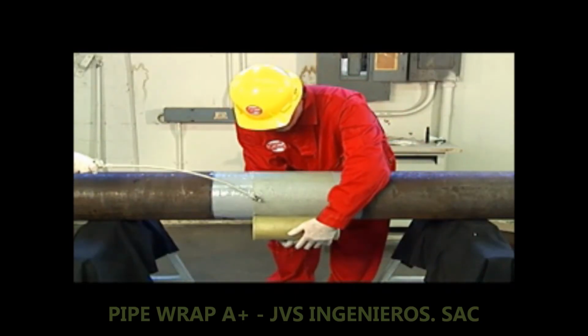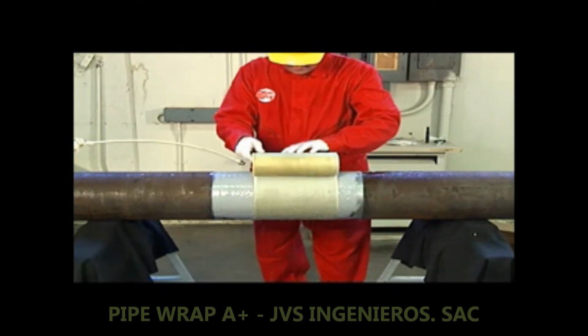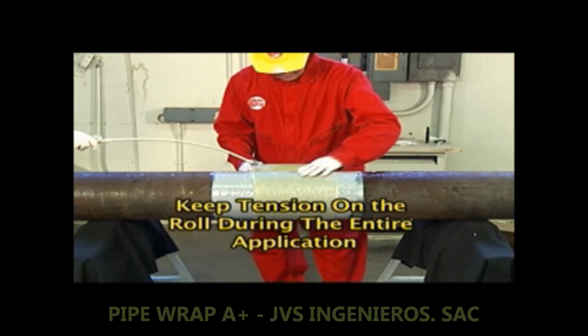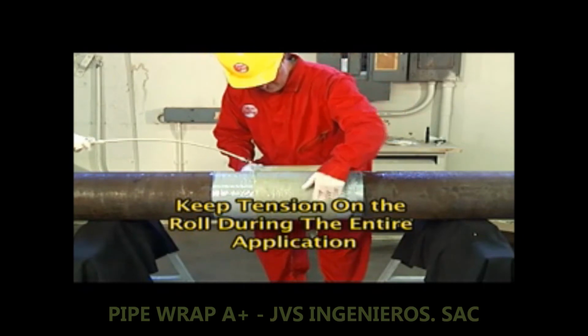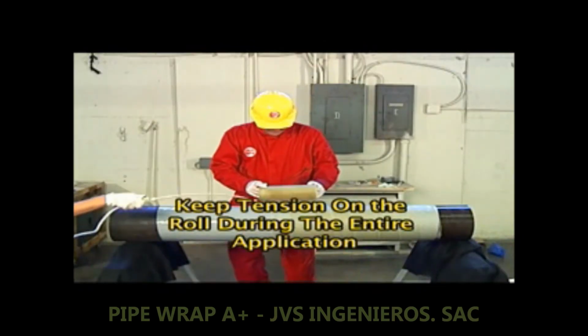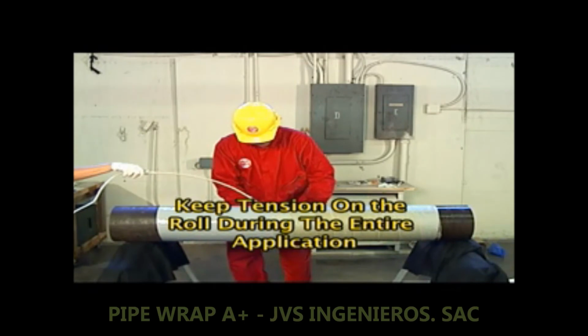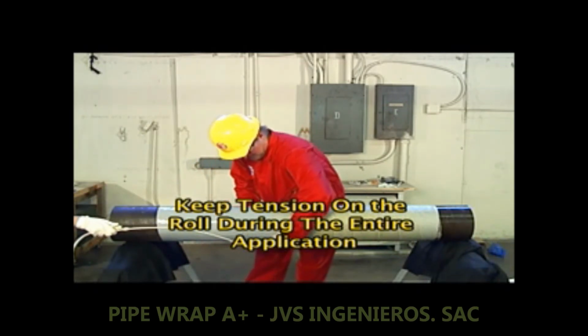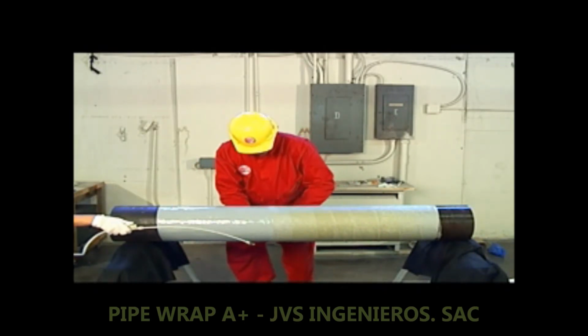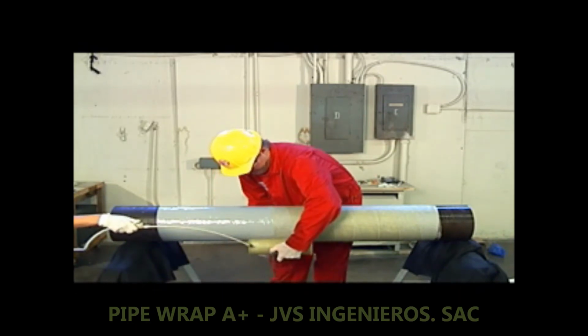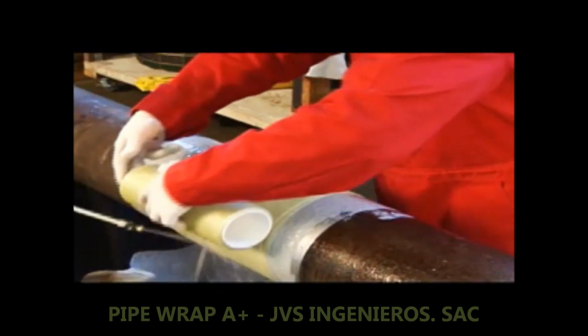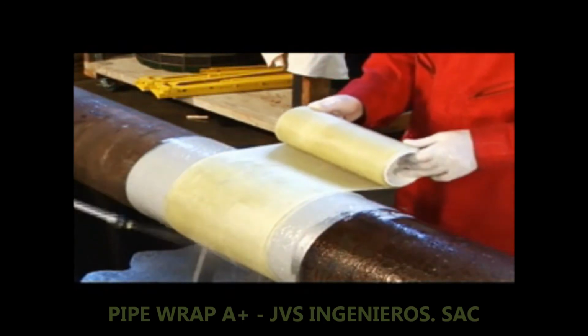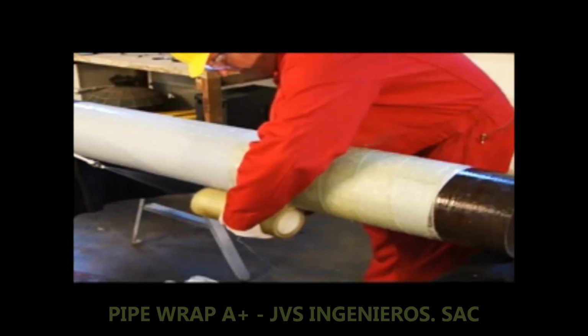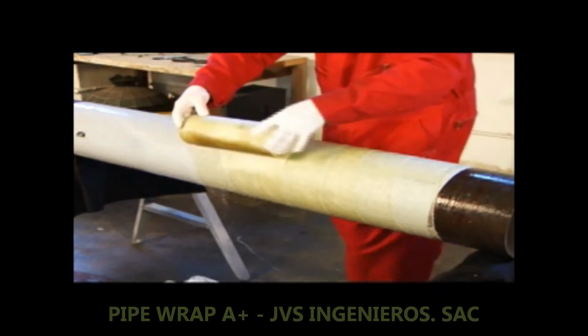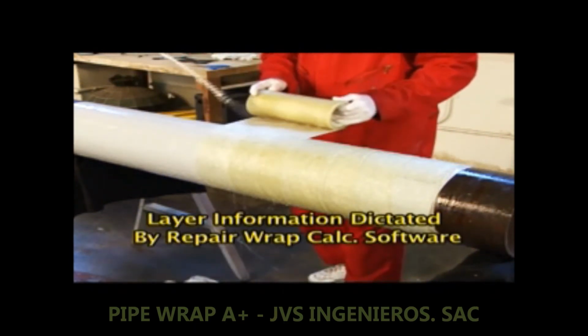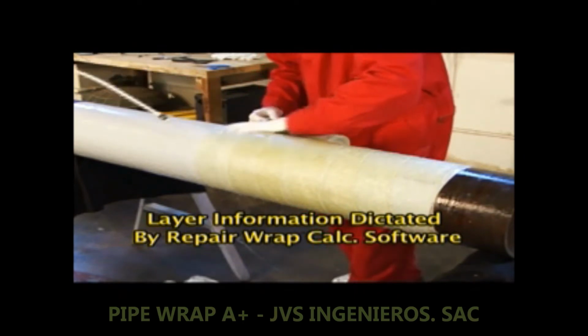There are two methods of applying Pipe Wrap A+ depending on the repair type. One method is the layer upon layer method of placing each layer directly over the previous layers. The second method is a spiral bias typically used for longer defects. This method requires there be a 50% overlap as the Pipe Wrap A+ is applied. Whether you're using the standard layer upon layer wrap method or the spiral bias wrap method, continue the wrapping until the desired number of layers is achieved, as dictated by the Repair Wrap Calculator software.